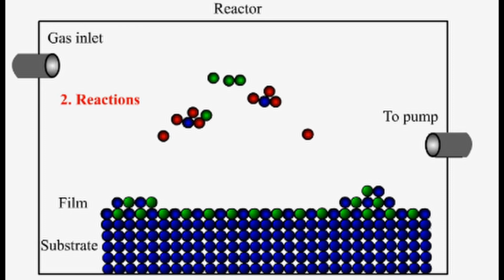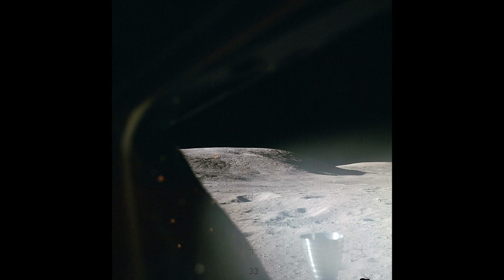The nature of chemical vapor deposition means that the fused silica is deposited very precisely, and engineers can highly optimize the properties. Since the glass has very few defects, the crack propagation is reduced, strength is increased, toughness is increased, and the optical properties are much more reliable. The glass is extremely clear, and it reflects so little that the Apollo astronauts were able to make orbital calculations based on markings placed on the window. The improved strength combined with its excellent thermal insulation and low expansion means that fused silica is very well suited for its job as a thermal protection layer.